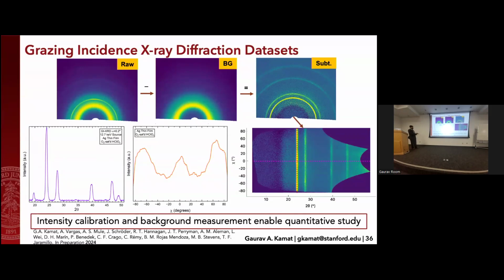And when we do an intensity calibration in this background measurement, because we just leave the cell in the same place and run an electrochemical protocol, we can actually enable a quantitative study where we can see differences in diffraction intensities and draw conclusions from the data.